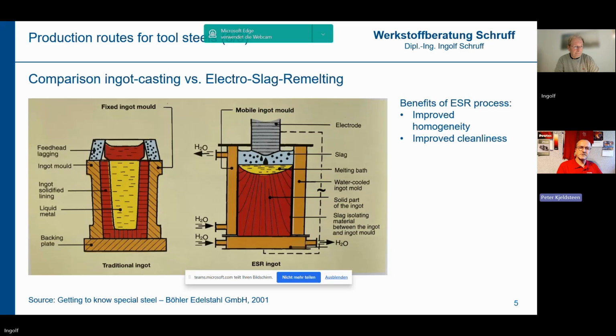So you keep it so long at such high temperature that even the chromium can walk around and homogenize and be distributed. It will, of course, not be a completely homogeneous material because nobody can afford that with today's energy prices. But from my point of view, it is not necessary to have it completely homogeneous, and it is probably not possible when you have a 20-ton ingot of hot work tool steel with, let's say, 1,000 millimeter diameter. You would spend days for such a process. So you transfer it into a good condition of microscopic and macroscopic homogeneity before you start forging.